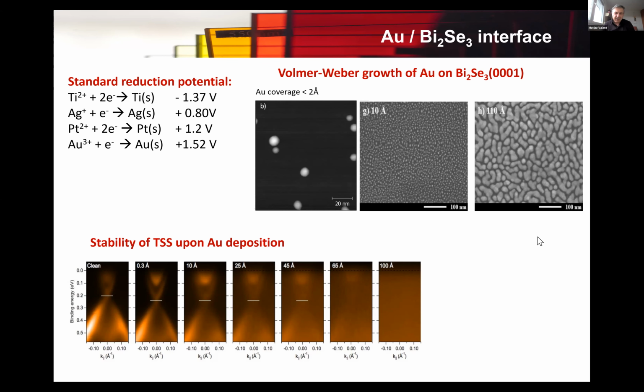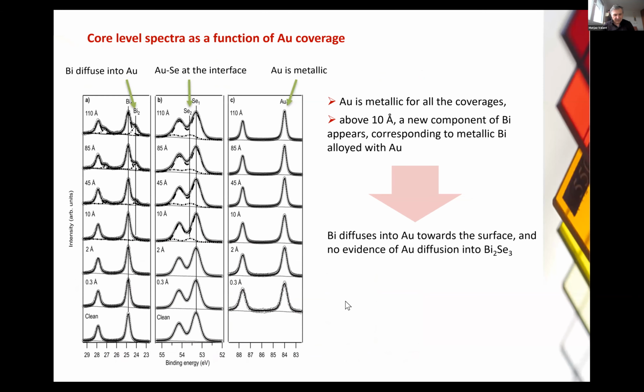So we measured the electronic structure of this system, and what we have seen is that the topological surface states are present in all cases. Of course, they're getting masked here by the presence of the gold layer. We cannot see them anymore at some point, but there is no band gap opening for sure. How about interaction? So again, we have done XPS to see the interaction.